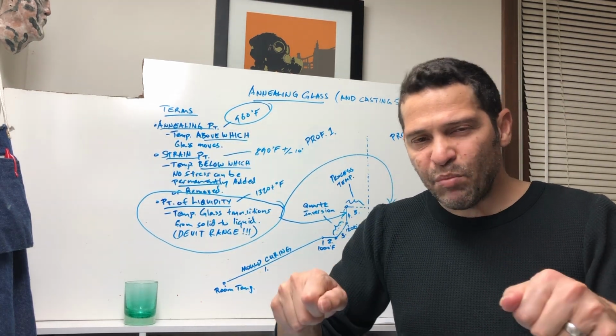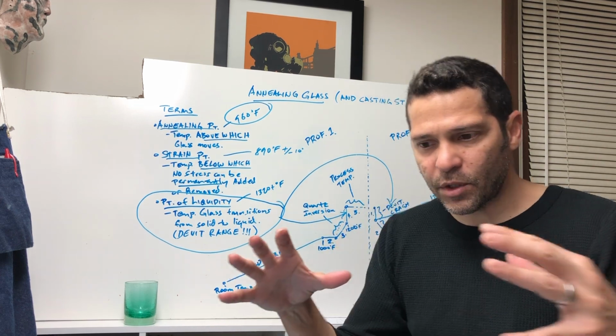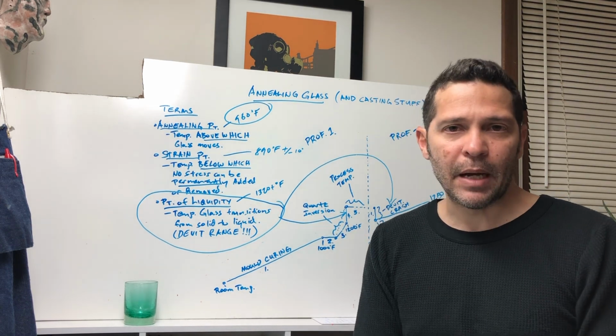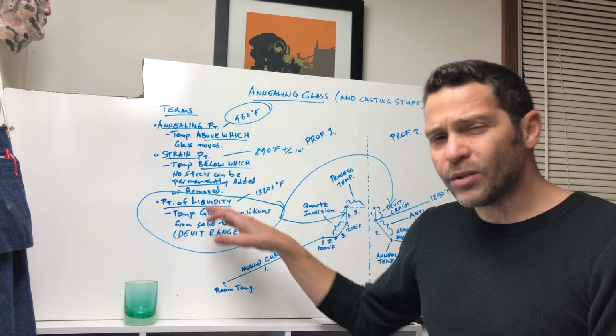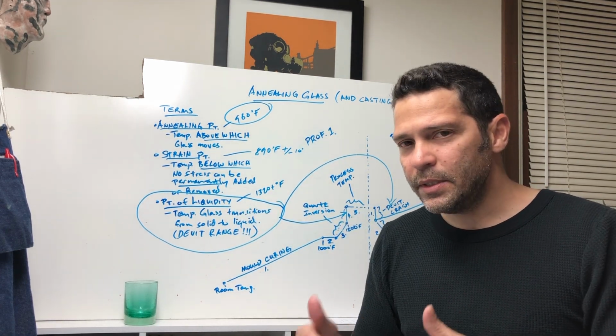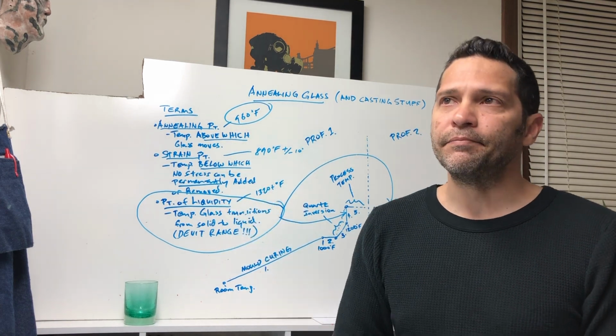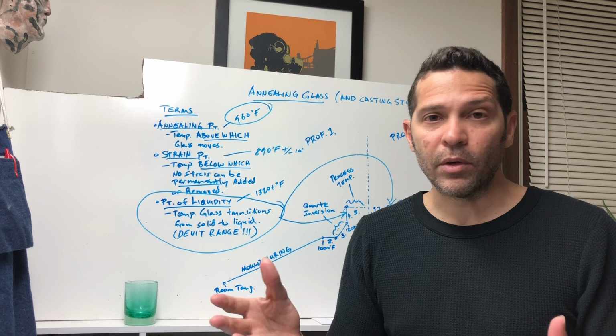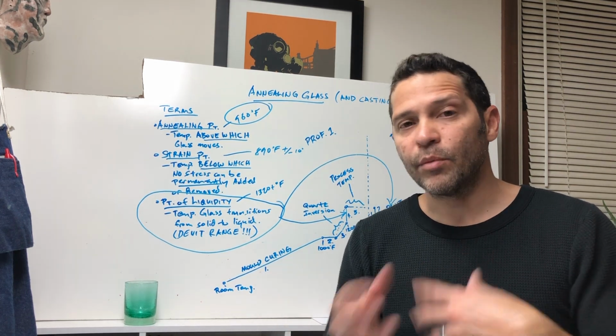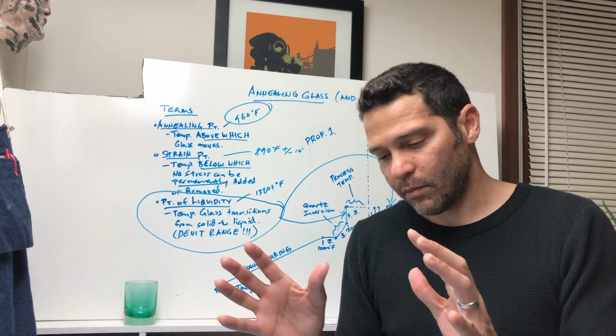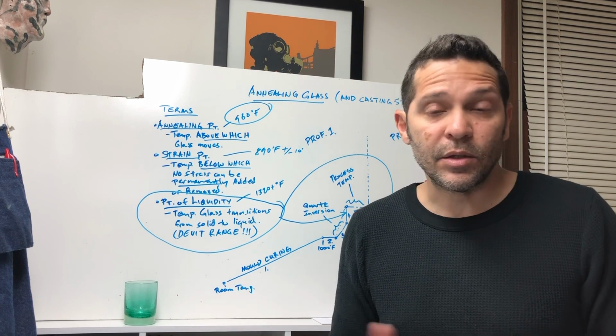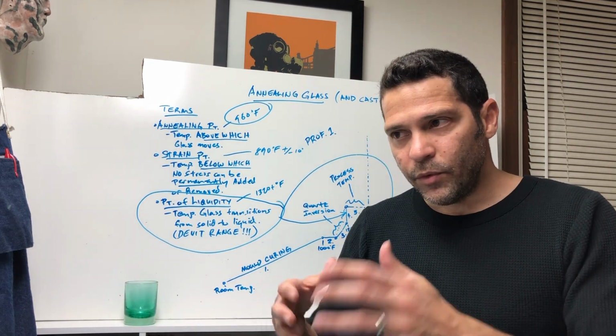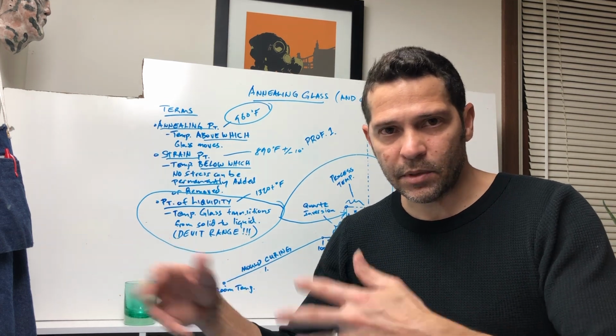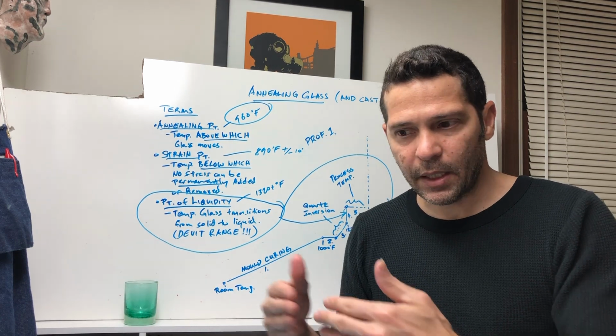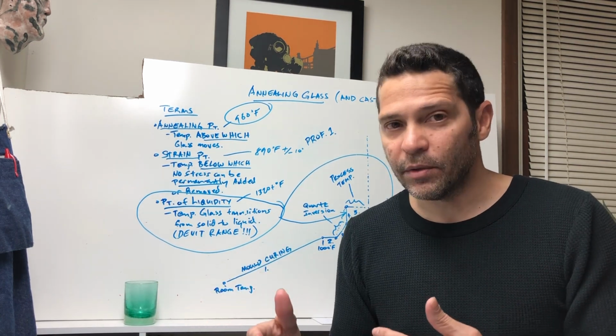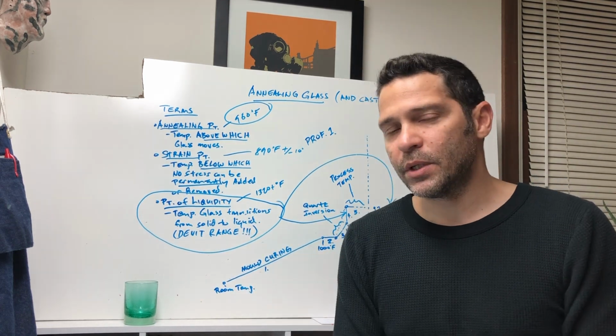That's where the glass starts just being bendy and starts to become a liquid and ball up on itself. The surface tension is broken and it wants to pull in and be that magic 6 millimeter thickness. That's also critically the point where glass wants to devitrify. So what's devitrify? When you take raw silica, soda, lime to make soda lime glass, you melt it. You take crystalline silica, and through the process of heat and other things, I'm not a chemist, you turn that crystalline silica into amorphous silica. Glass is an amorphous solid, not a crystalline solid. Vitrification just means to turn something into glass, to melt it. If you devitrify it, it turns it back into those crystalline materials. You're taking the material that makes up glass and turning it back into its constituent parts in a way.